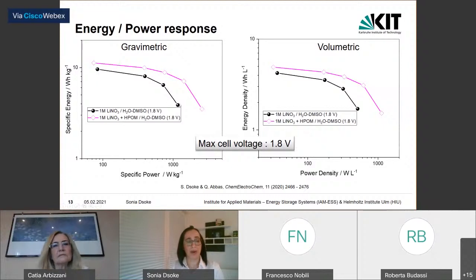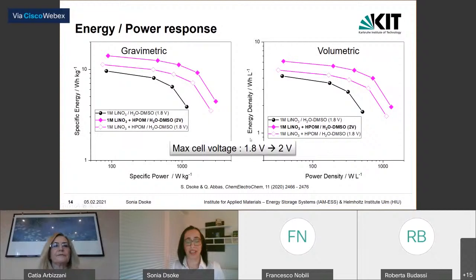And when we add the polyoxometalate to the system, we can observe an increase in the energy for every power, both in the gravimetric and volumetric energy and power. In this case, the maximum cell voltage was kept at 1.8 volt. We know that by increasing the potential, since the energy depends on the cell voltage, we can of course increase also the energy density, as you can see from this third curve here.